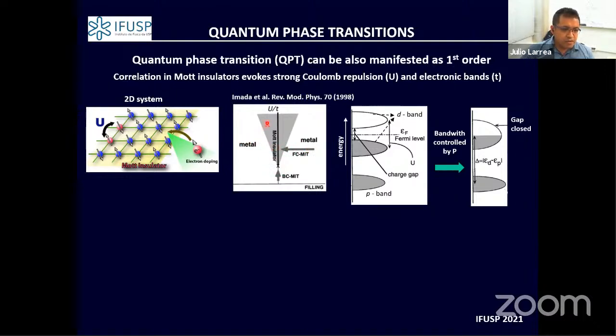Or if you stay from one point inside the Mott Insulator phase, what you expect is that at the beginning you simply have a gap opening in the conduction band. But by applying pressure in this direction, you start to narrow this conduction band and close the gap, inducing a metallic phase.